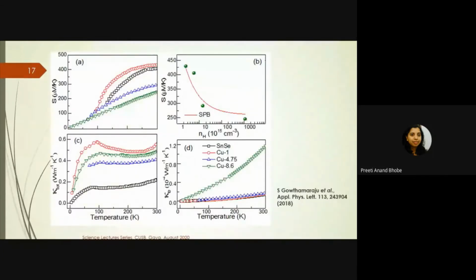If we look at the Seebeck coefficient, the corresponding Seebeck coefficient does come down. So what did I achieve then? If my Seebeck coefficient comes down, then the thermoelectric performance is coming down, but not necessarily. The overall performance will be measured by ZT, the relative change. Compared to SnSe, which had a Seebeck coefficient of around 400, it comes to half of that value, at around 200, when you put in copper.